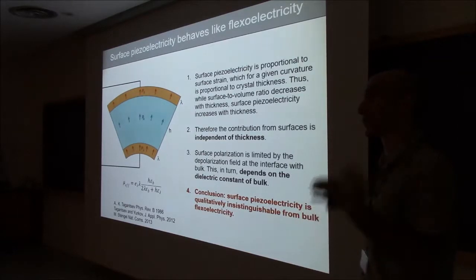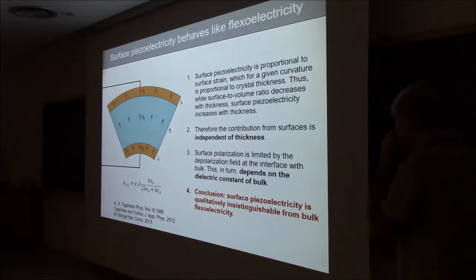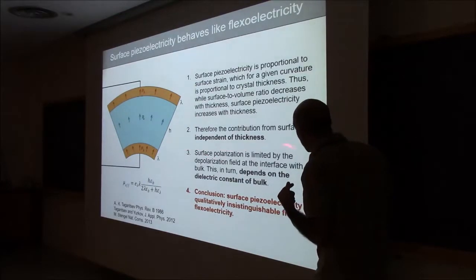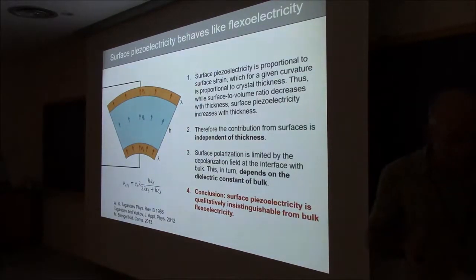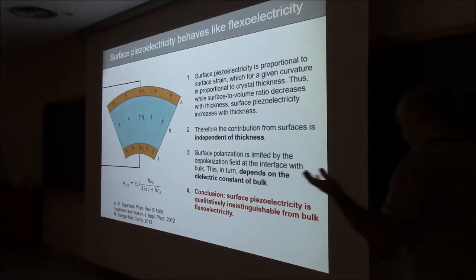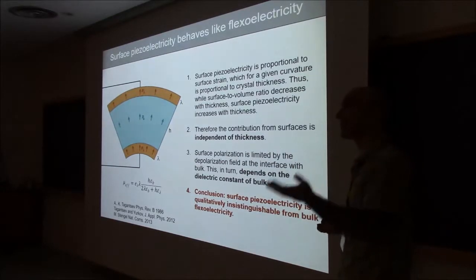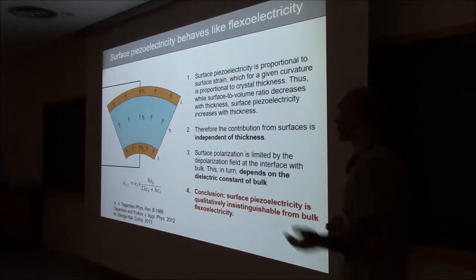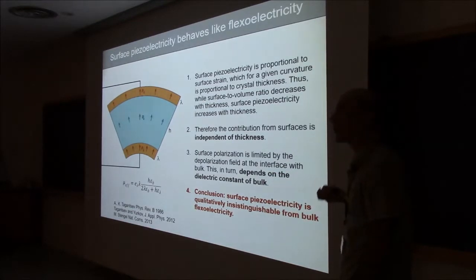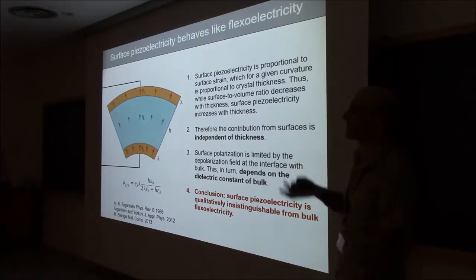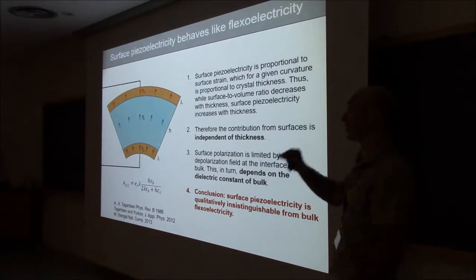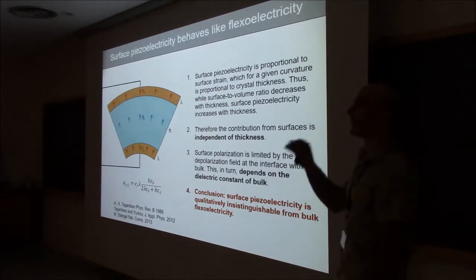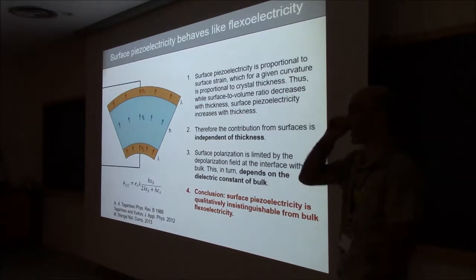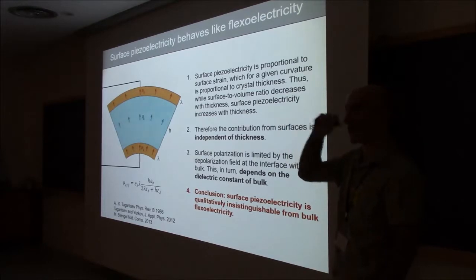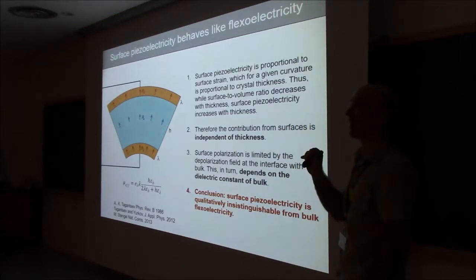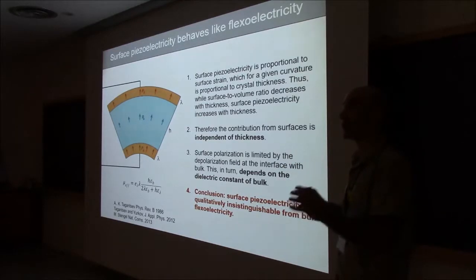Surface piezoelectricity does not depend on thickness. And this is very profound. It's so profound that, I think David mentioned Max Stengel. He's a theoretician who works in Barcelona on the theory of flexoelectricity. And he is the first one who told me that in theory, if you take a strontium titanate single crystal and you just change the surface termination from being TiO2 terminated to SrO terminated, so just the last atomic layer on your 1 millimeter thick single crystal, the sign of the total flexoelectric current should change.